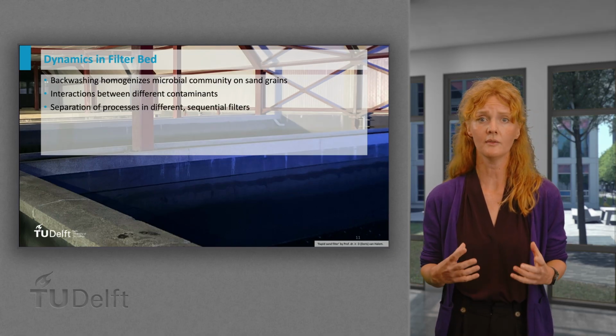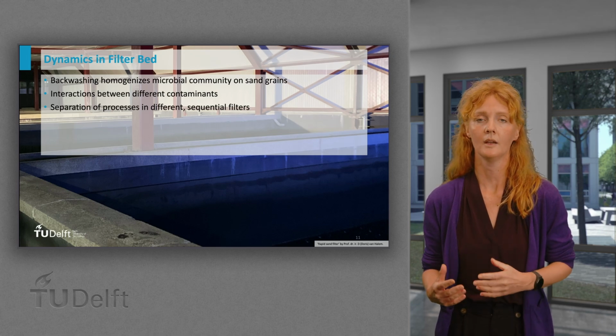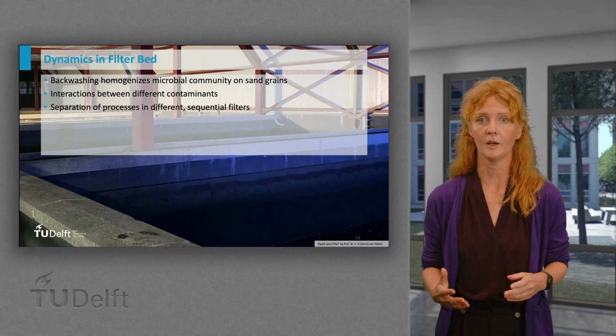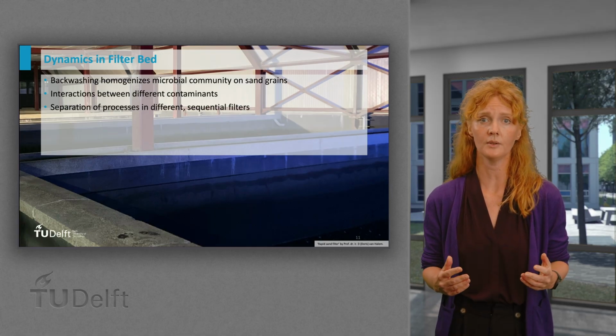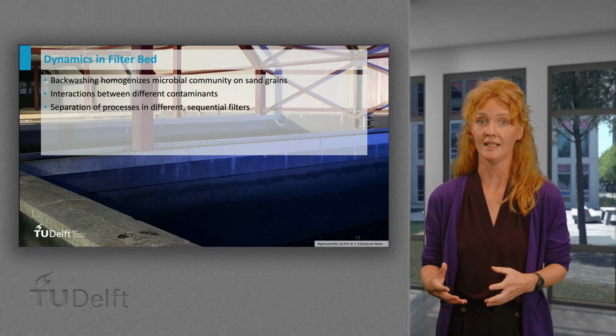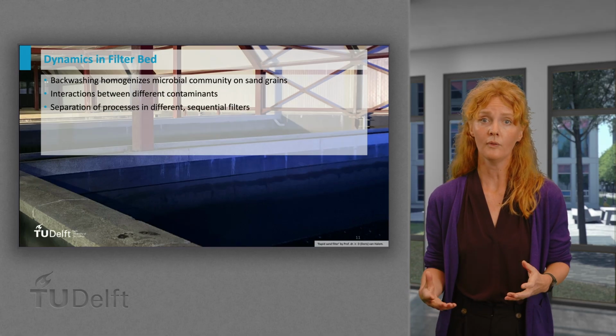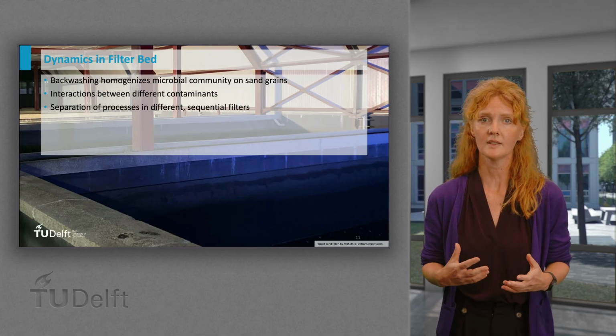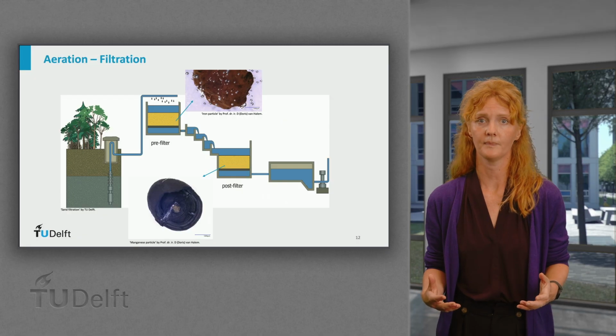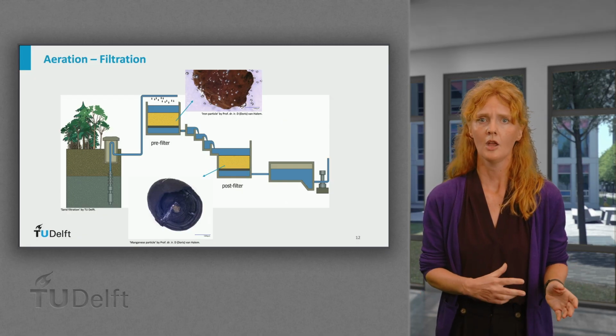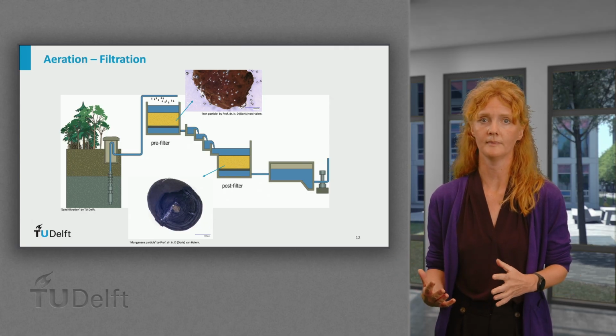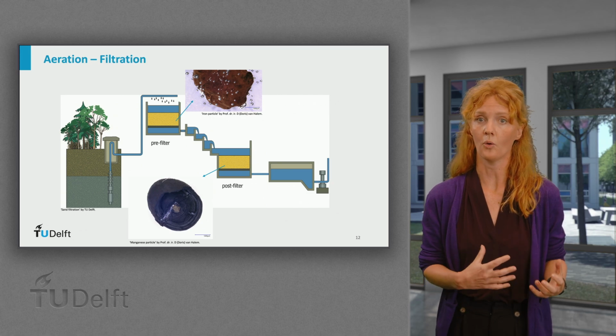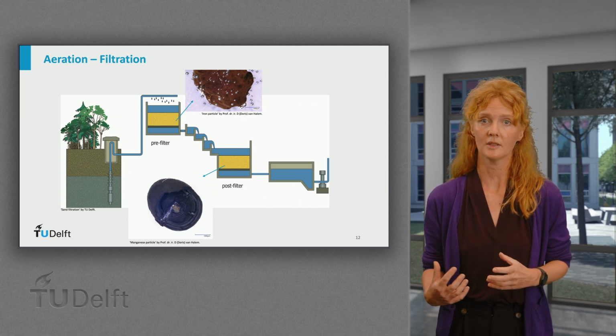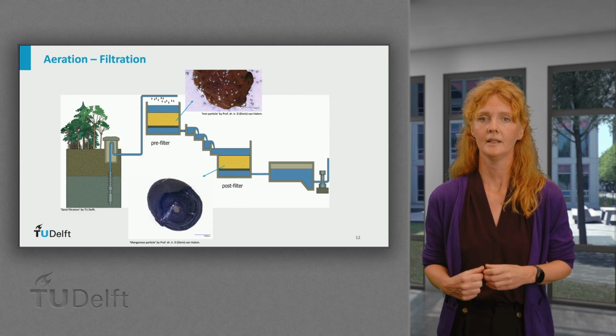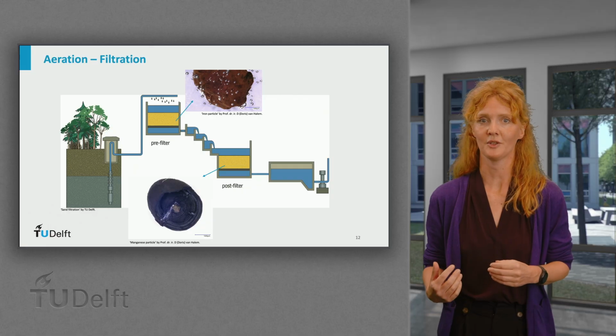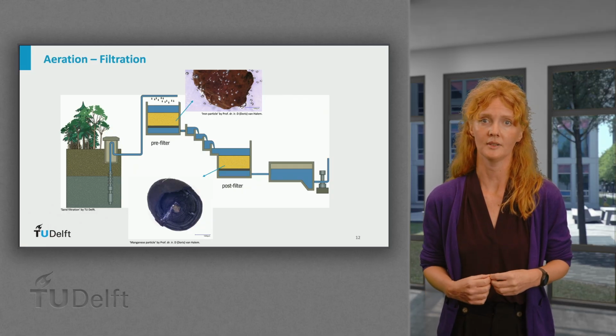As a consequence, various conversions in the filter bed may interfere with each other. For example, nitrification is known to be hindered by precipitating iron oxides. Also, the onset of manganese removal is known to be delayed by incomplete nitrification. Well, to avoid such undesired interactions, one could separate these processes into different sequential filters. In pre-filters, iron oxidation will dominate, whereas in the post-filter, ammonium and manganese removal occur. As a consequence, the pre-filter will contain orange iron oxide-coated sand, whereas the post-filter will contain black-colored manganese-coated sand. In practice, iron carryover from the pre-filter is observed, so the black coating will also contain impurities of iron.